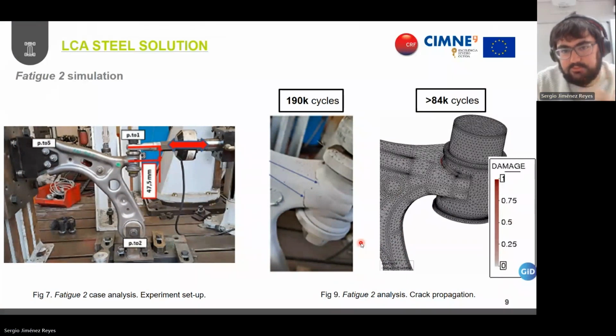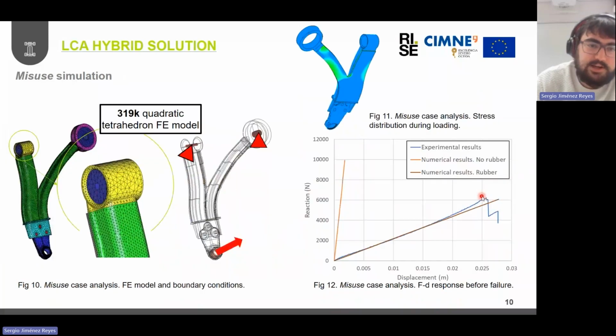Let me just look through the video, just to show you this progression. And of course, we are not matching, as Michele mentioned, this amount of cycles compared with the experimental result. But this may be due to the huge uncertainties coming from the welding in this region here. But at least we can capture the failure mechanism and the crack taking place. And with this, I finish with the steel solution for the lower control arm. And now we move towards the hybrid solution.